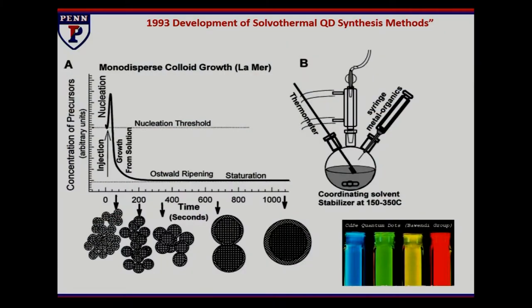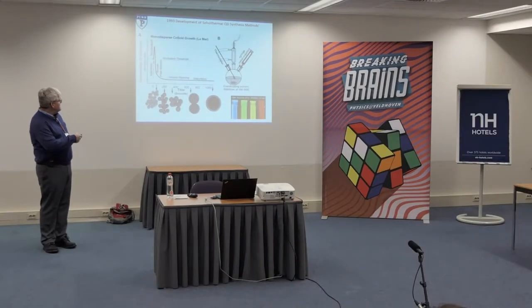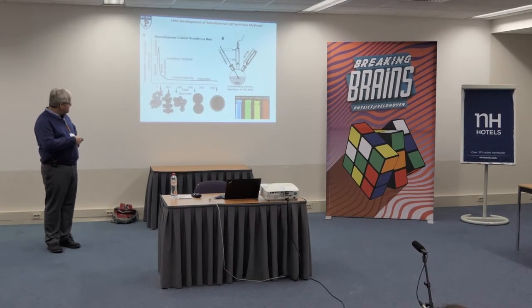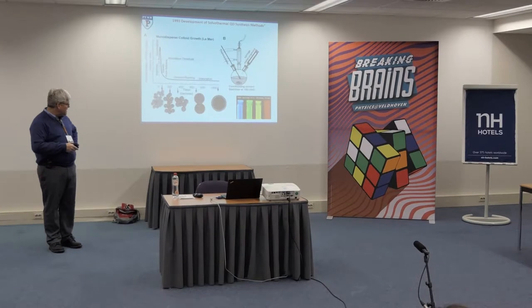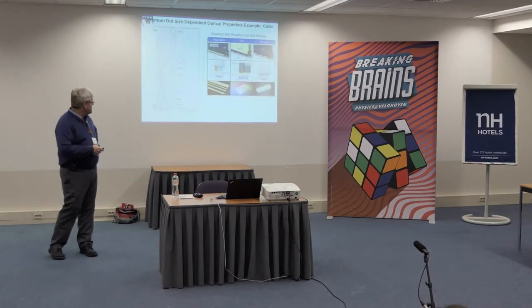If you have those conditions, you have set up a growth environment that can lead to a narrowing of the size distribution as the system proceeds. In some cases, Ostwald ripening, which is a process of materials transfer from the smallest particles to the larger in the group, helps to nudge this along in its growth. But a number of mechanisms can be important in this piece.